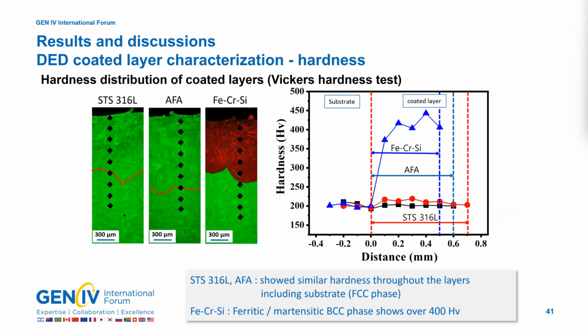To determine the hardness distribution of the coated layers, a Vickers hardness test was performed. STS316L and AFA showed similar hardness throughout the layers, including the substrate. But iron chrome silicon exhibited hardness values over 400 HV.